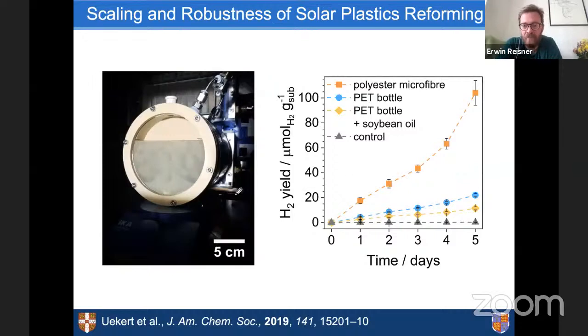And then we also start thinking slowly about scaling. When I say scaling, this really comes from an academic laboratory. We look here at 10 centimeter, maybe diameter. The solution has about 150 milliliters, but also these systems here photoreform equally well. You can see the hydrogen yield. What we have in here is polyester microfiber, which of course is great for us because it's quite well suspended in the solution, but you can also use bottle. And the particular strength here is we can use contaminated waste. So even if we have some soybean oil on the PET, it's not really a major issue, it still works to some extent.